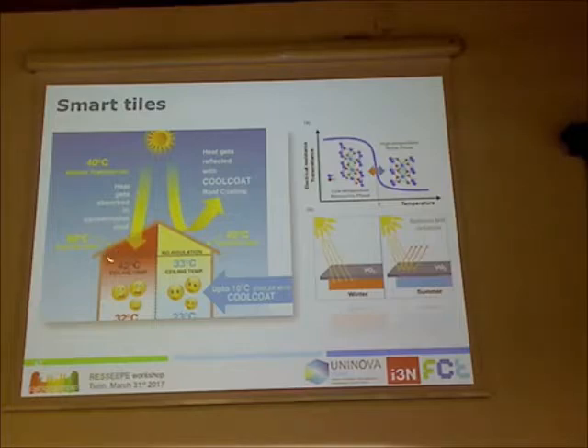It's very easy in the summer for the roof to reach 60 degrees under direct sunlight. But if you reduce the critical transition temperature, even better. I already told you that doping can do that. If you dope vanadium oxide with tungsten oxide, mixing in a slight amount, 3% by volume, you can reduce the transition temperature from 68 down to 40-42 degrees, which is very easy to achieve on a sunny summer day.